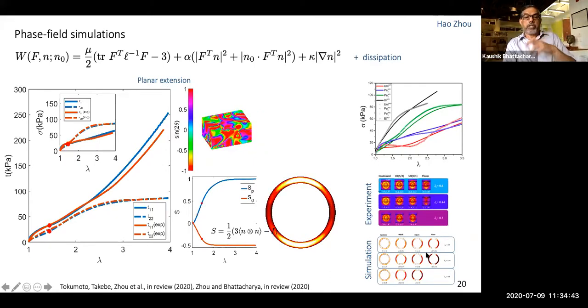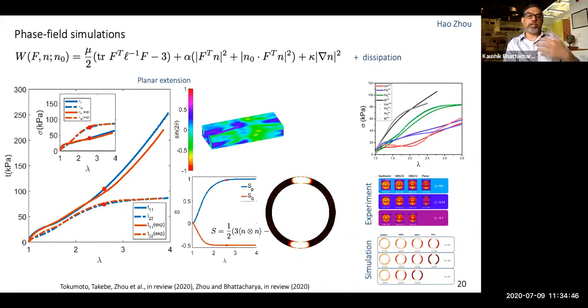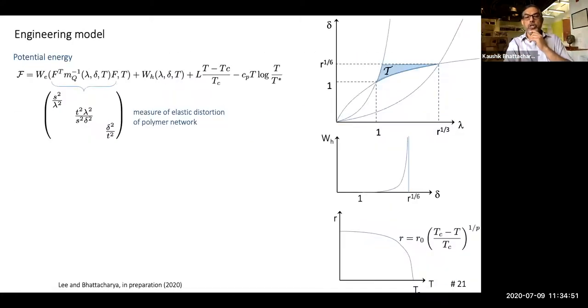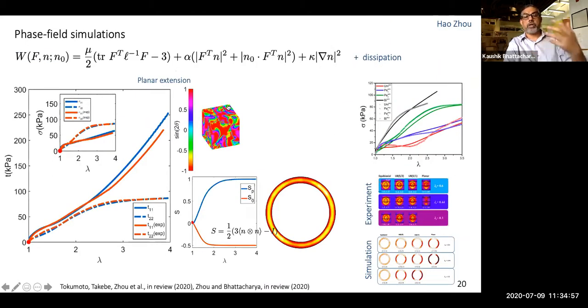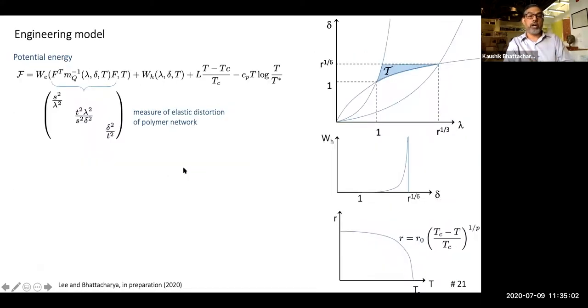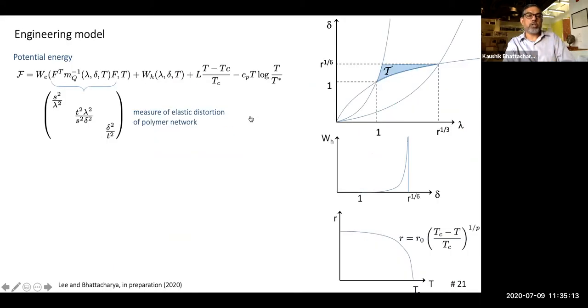Okay, but simulations like this also give you insight into how the overall microstructure is evolving, and you can use that to build engineering models. In engineering, you can't describe material behavior at each point with this level of complexity, so you need a very simple model, and it turns out that you can build this model in this way. What the simulation shows you is how this microstructure evolves, and you use that to understand the elastic distortion of the matrix with all this complicated behavior going on inside.